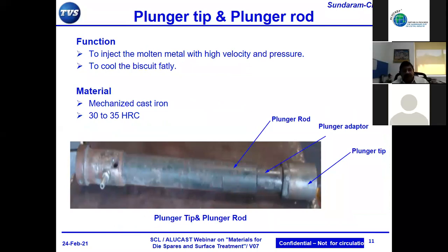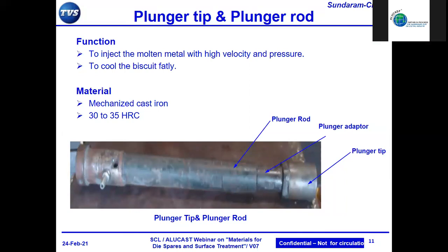So here within the short sleeve, we have a plunger, a tip and a plunger rod. We have different kinds of plunger tips and plunger rods which are used. A Copromac with a steel ring is one which is used recently, but then the age-old mechanized cast iron material is used. And again, this is to inject the liquid metal with a high velocity and pressure and to cool the biscuit fast. So this needs to cool the biscuit very fast, so you need to have a high conductivity. You have a water cooling arrangement. So corrosion resistance and all these things need to be built into the material requirement.